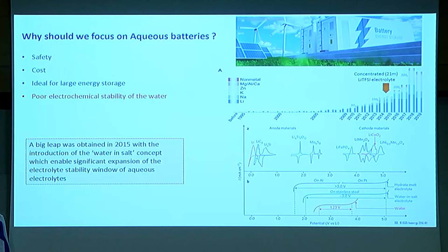So why aqueous batteries are interesting? We are thinking about large energy storage. And in large energy storage, we should use large amount of mass, large amount of batteries, and large amount of electrolyte as well. So in this case, we cannot use flammable electrolyte, and we should also consider the cost of the electrolyte. So for this, water electrolyte may be the ideal solution for large energy storage. However, we all know that water electrolyte has very poor electrochemical stability, and we are limited to about 1.2, 1.3.